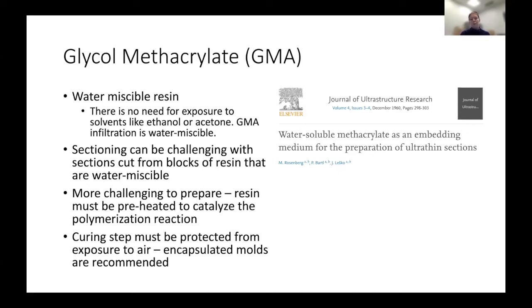Oh, yes, when you cure it, it needs to be protected from exposure to air or it doesn't cure completely. It'll have a layer of uncured polymer on the surface, which can make a mess. So it's recommended to use encapsulated molds like beam capsules or gelatin capsules, or even if you want to use a plate mold, you can just cover the thing with paraffin or ceramic, as long as it's airtight. It should be fine.